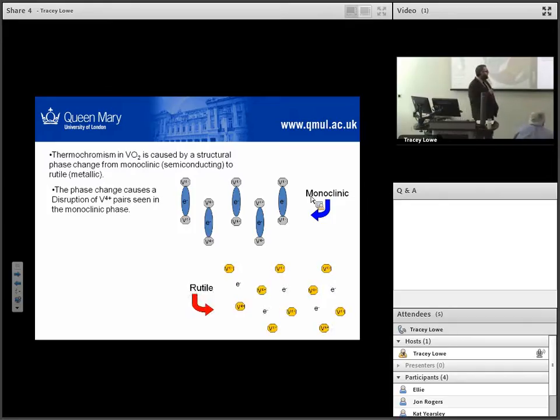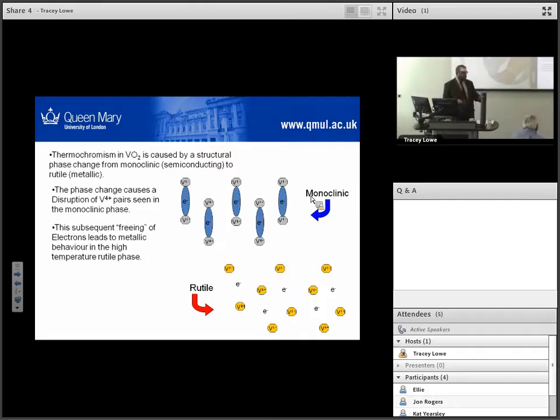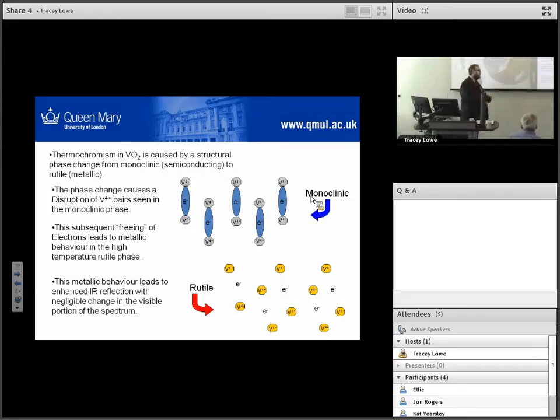When you get warmer, you get some disruption in the crystal structure when you go to the rutile phase, and suddenly you no longer have this overlap of these DZ squared orbitals, so you lose that band from your band structure. These electrons become free, but they have to go into a different band in your structure. They don't quite fill it, so you get metallic behavior.